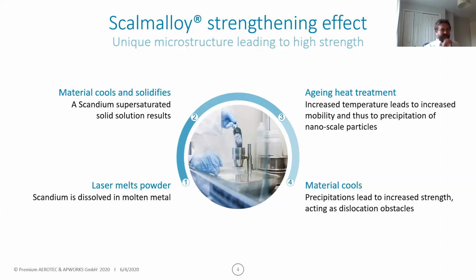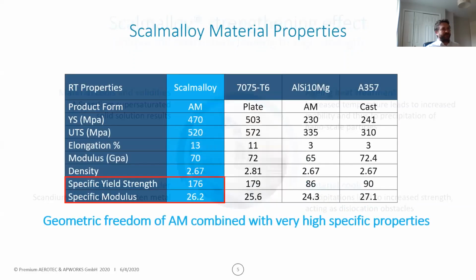And it's kind of weird. It looks like a night sky if you look at it. In an SEM image, you see all these tiny little pinpricks of these precipitates, which are nicely dispersed because they have been maintained in the supersaturated solution. And this is giving you these, let's say, dislocation obstacles, which are giving you this very high strength. And as I said, the beauty there is high strength with ductility. But the reason no one thought of doing this before is if you just try to cast this material, for example, with low cooling rates, you would simply have a material full of large defects that would actually act against you. So it really does rely on the cooling rates of additive manufacturing.